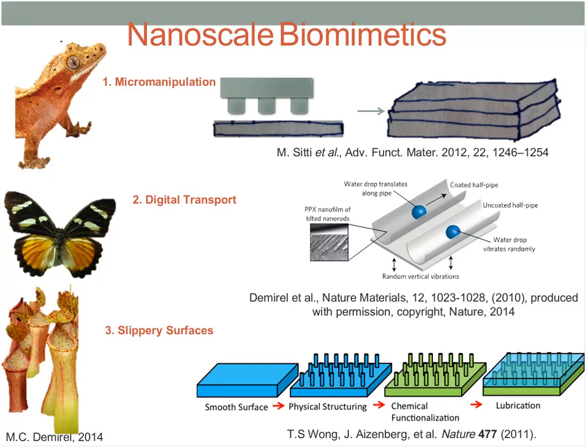The second example is from my group. We reported an engineered nanofilm composed of an array of nanorods which demonstrate asymmetric wetting behavior by means of a pin-release droplet ratchet mechanism. The nanofilm provides a microscale smooth surface on which it transports microliter droplets, and it is also relatively easy to synthesize by a bottom-up vapor phase deposition technique. This work was published in Nature Materials in 2010. We also demonstrated the actuation of microgel encapsulated in droplets using these surfaces, which offer a pathway towards high throughput microgel assembly applications to build complex constructs.